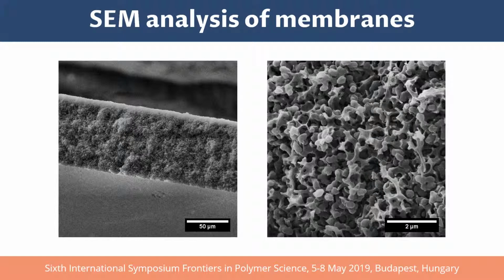We also examined the microstructure of the membranes and implants. The membranes are quite porous and have an approximate thickness of 85 microns in the dry state. Hydrogel-rich particles of submicron size in the dry state are attached to the porous hydrophobic support.